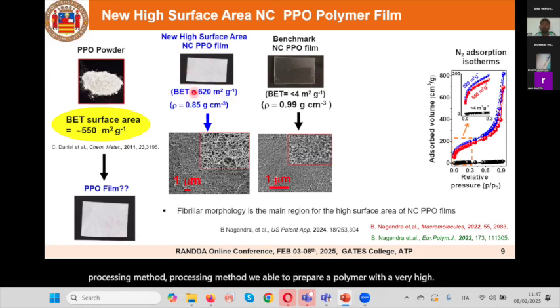This surface area is more than the powder, so this is really surprising. Generally films have a negligible BET surface area, only four, but these films are very huge, more than the powder. So these are completely surprising results. And you can see the density of the benchmark film is 0.99, and our film is also near this. So this confirms this is definitely a film, but the surface functional properties are completely different. This difference in surface property is mainly due to a unique kind of morphology, a fibrillar morphology, which mainly drives the high surface area.